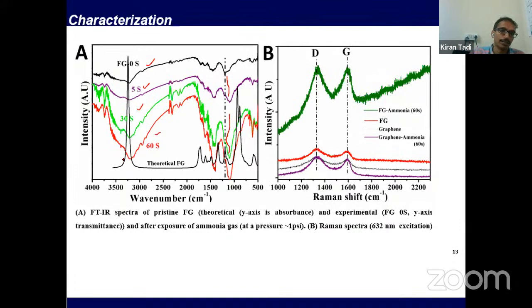Theoretically also we did the FTIR spectra, shown vertically here, and this also has the characteristic peak of the CF bond, exactly matching the experimental value. This FTIR spectra gives strong confidence that my ammonia molecule is interacting with the fluorinated molecule.